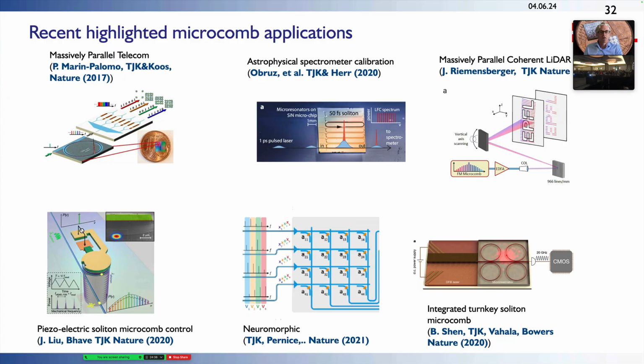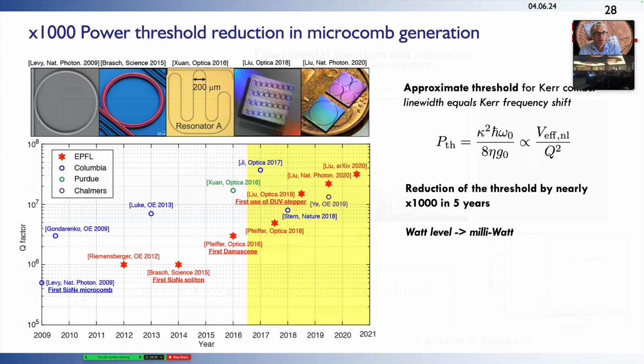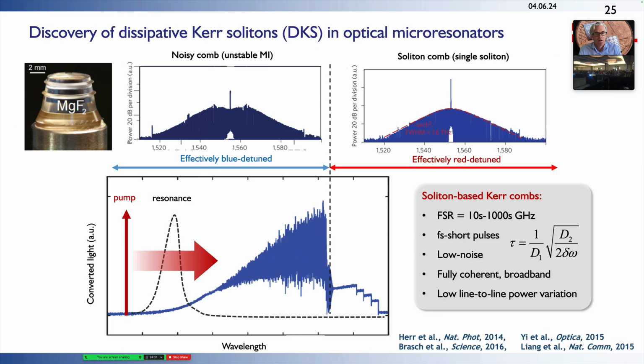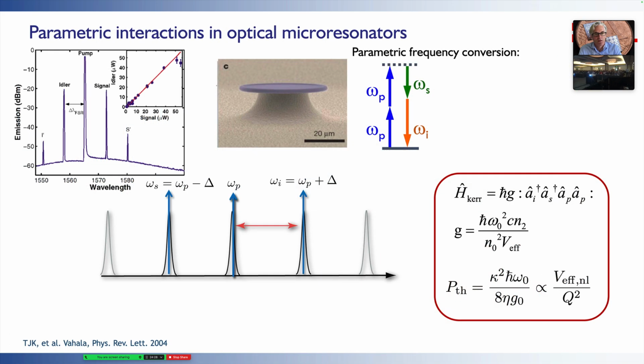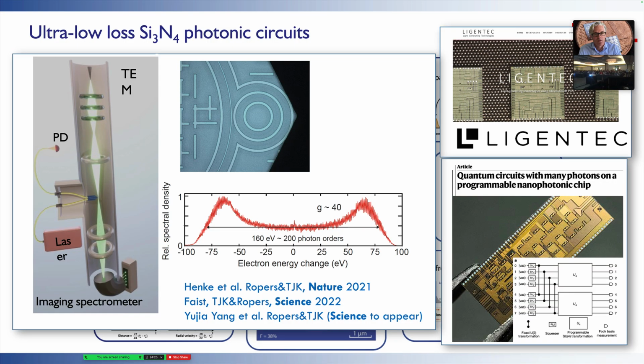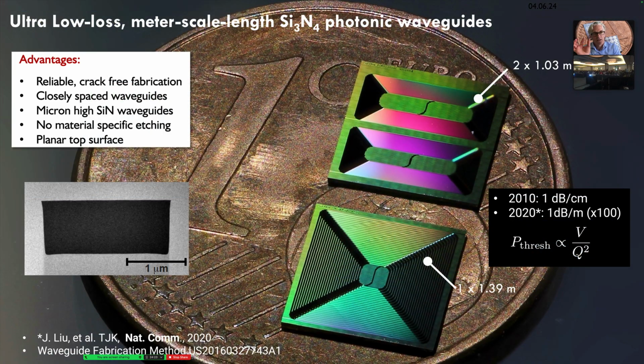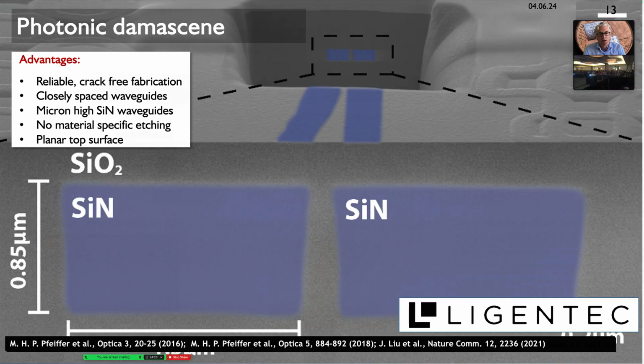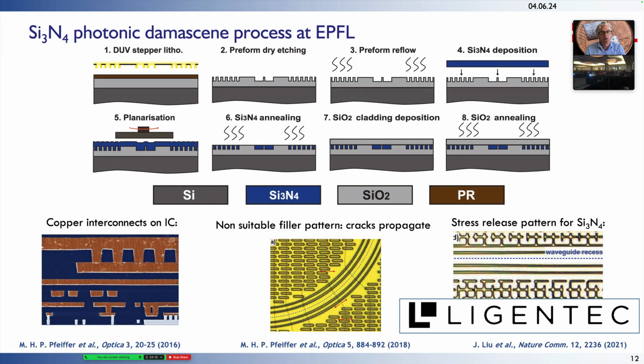So the limit of the height, going back to the Damascene process, the limit of the height of the waveguide is simply given by the aspect ratio we choose of the openings, of the waveguide width to height. In our work we have created waveguides as high as 1 micron. The problem is if we go more than 1 micron, at some point the deposition itself becomes unstable, so it's hard to avoid crack formation. So up to a micron is what we can comfortably do in this Damascene process.